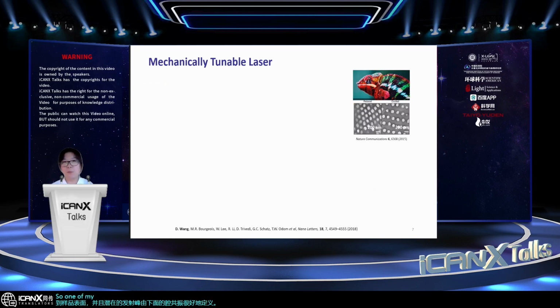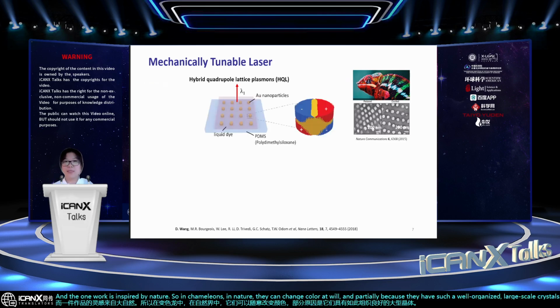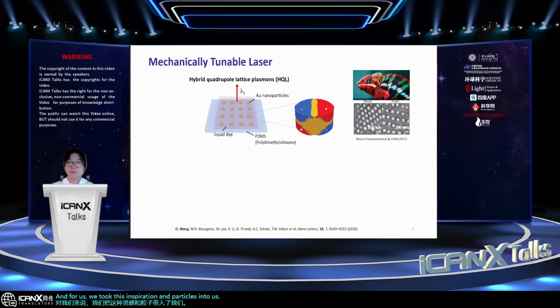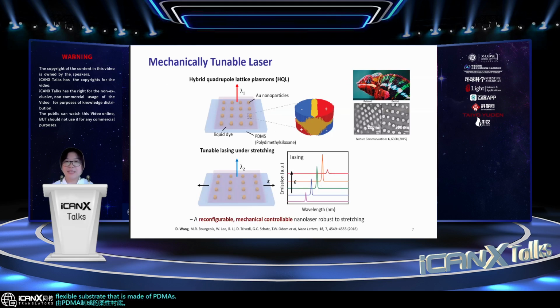One of my works in the past focuses on the structural engineering of nanoscale cavities for different functionalities. One work is inspired by nature. Chameleons in nature can change color at will, partially because they have well-organized nanoscale crystals on their surface. We took this inspiration and put the particles into a flexible substrate made of PDMS. Upon stretching and releasing the substrate, we are tuning the interparticle spacings mechanically by the strain. This modulates the optical resonance of the cavity and controls the laser emission mode. As a result, we see this mechanically tunable lasing based on the local strains that is robust to the stretching.